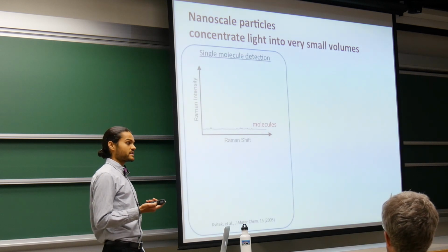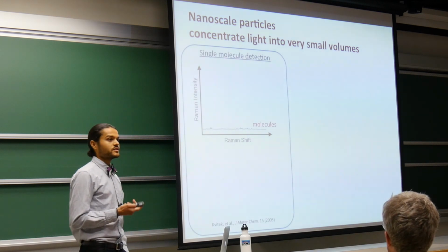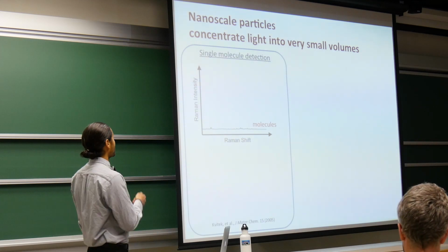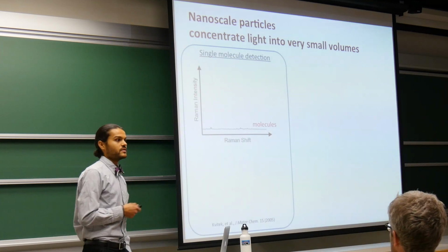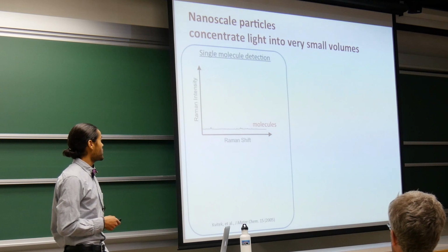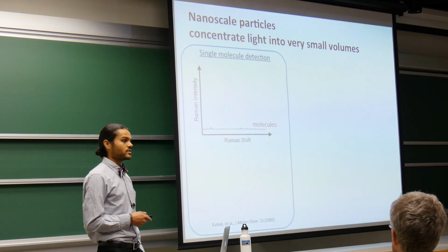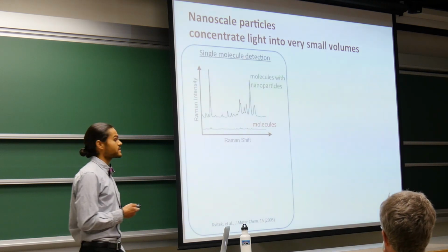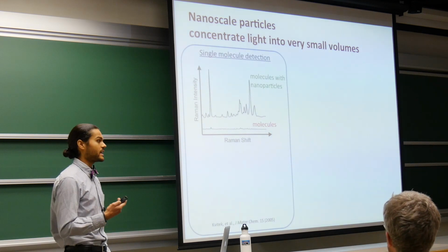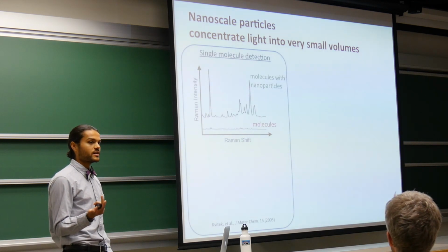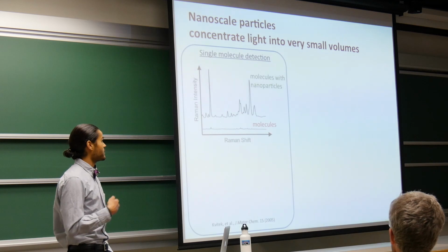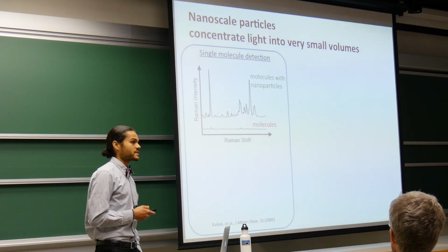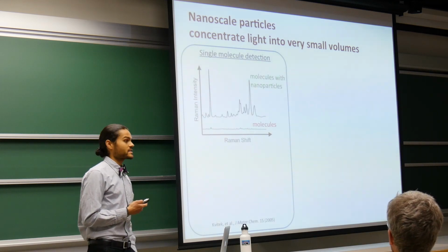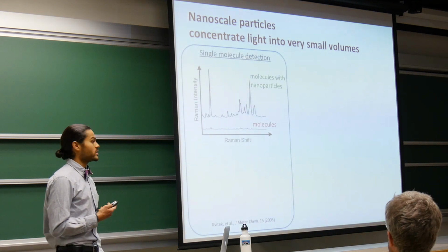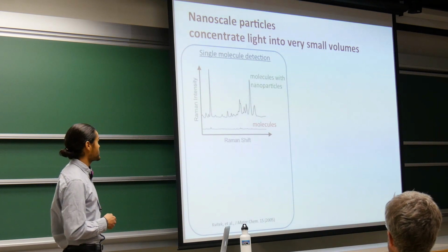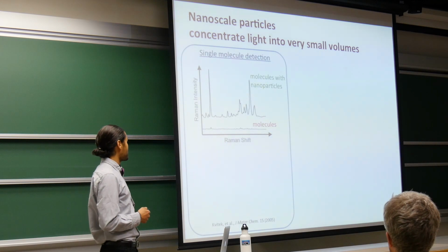However, unfortunately, this process is quite weak, and so if we have a very dilute solution of molecules and we look at the Raman intensity as a function of the Raman scattering energy or Raman shift, we see basically very little signal. Now, if we place these nanoparticles in the solution, they can concentrate the light at the nanoscale. It can increase the interaction of the light with these molecules and therefore yield a larger Raman scattering signal. This process can be so effective, actually, that we can detect single molecules using this particle-enhanced Raman technique.